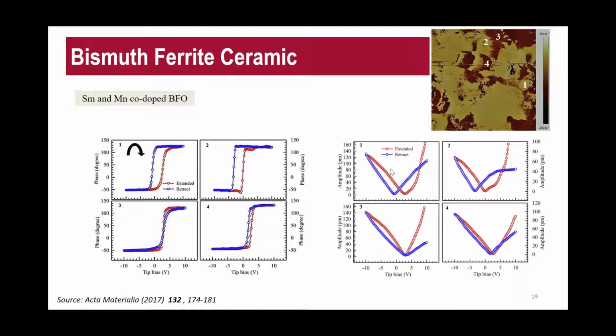So what we are trying to show here is that PFM is able to help us look into very detailed information, especially in localized regions, in the case that each of these could have a different behavior. For example, in terms of the hysteresis slope, you can see from 1 to 4, the behavior is different in terms of the ferroelectricity as well as the piezoelectricity.